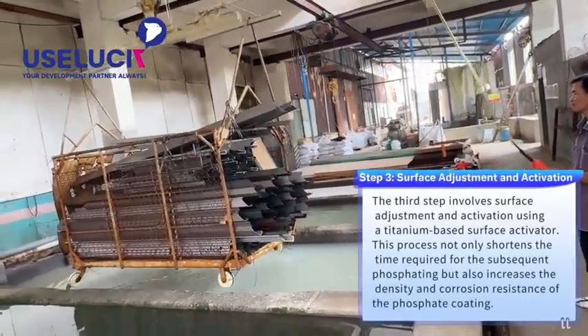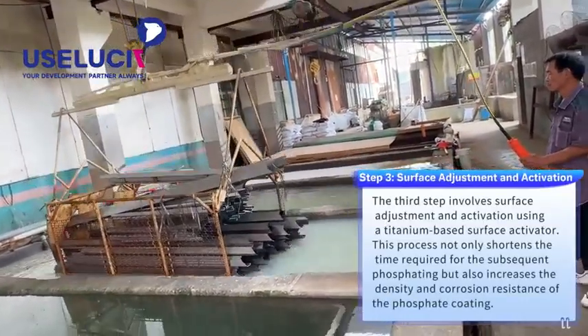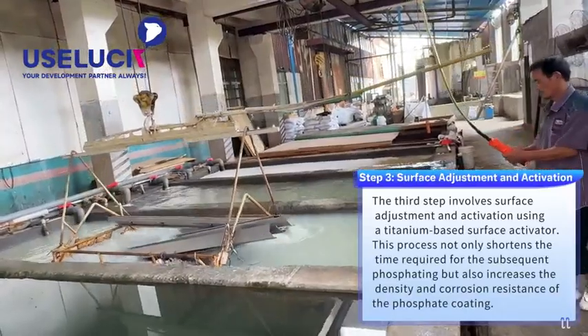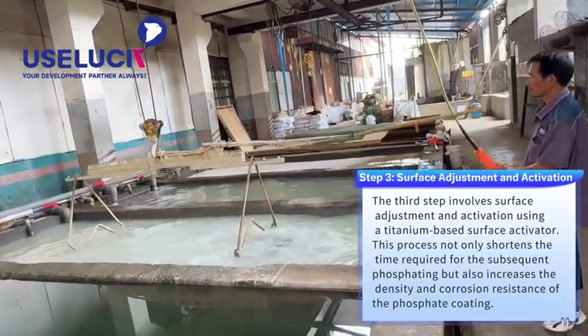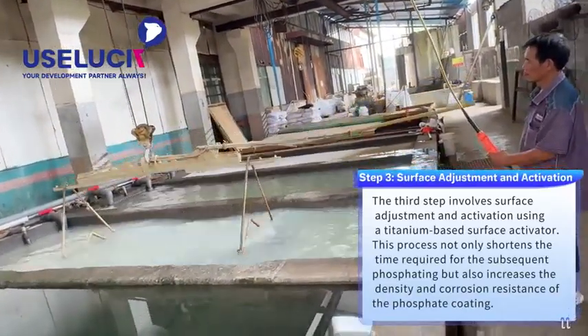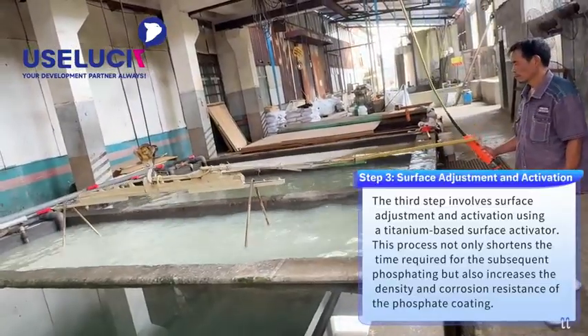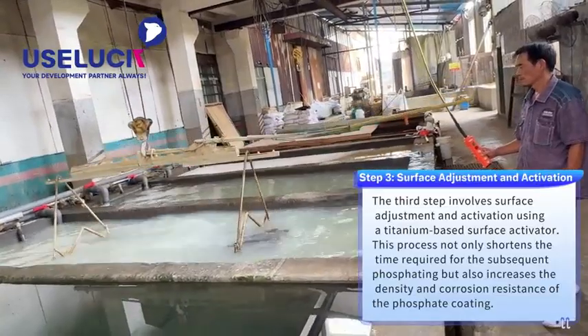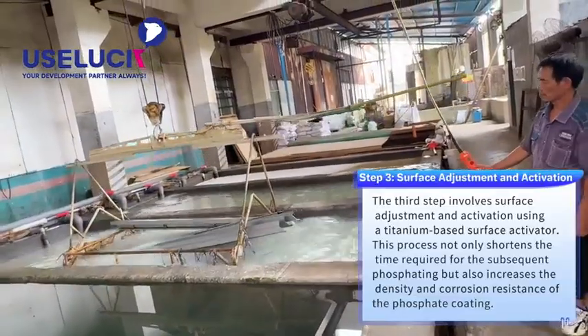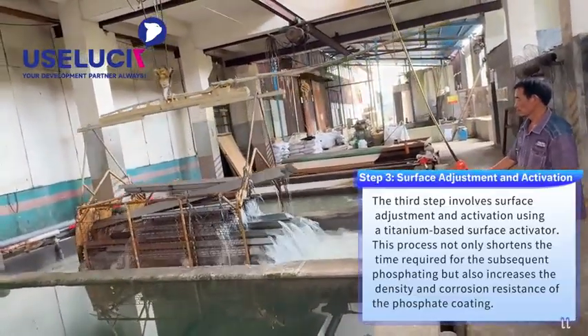Step 3. Surface adjustment and activation. The third step involves surface adjustment and activation using a titanium-based surface activator. This process not only shortens the time required for the subsequent phosphating, but also increases the density and corrosion resistance of the phosphate coating.